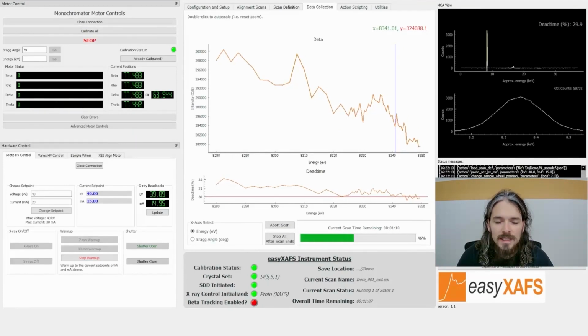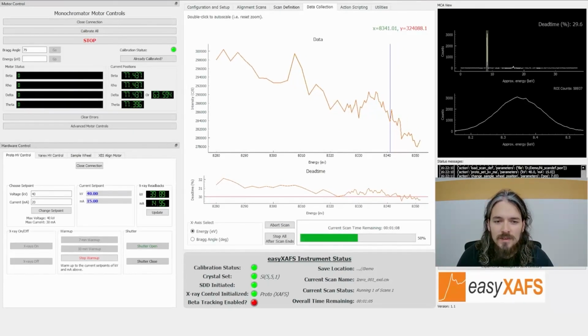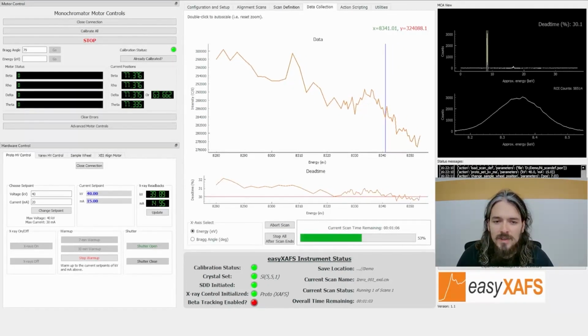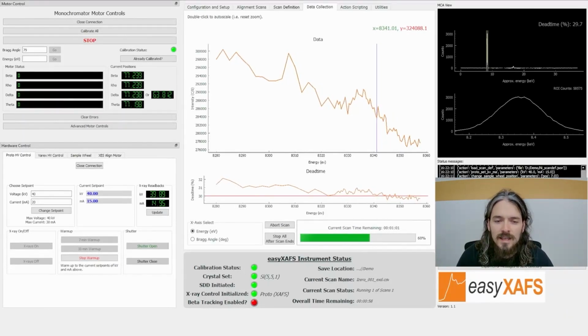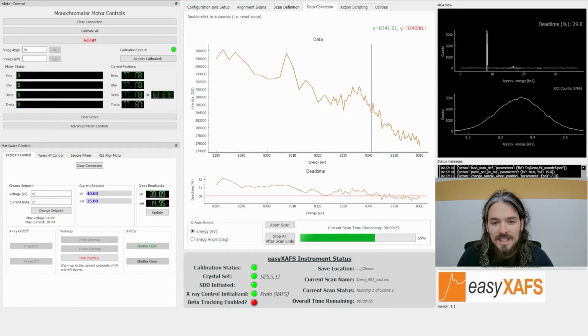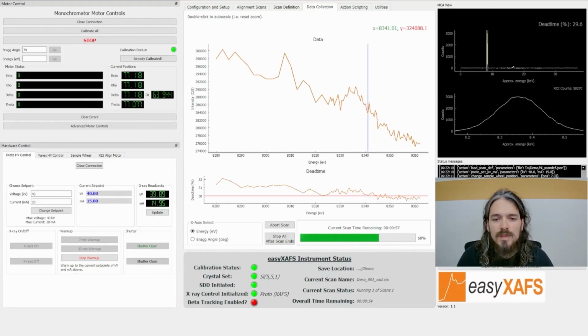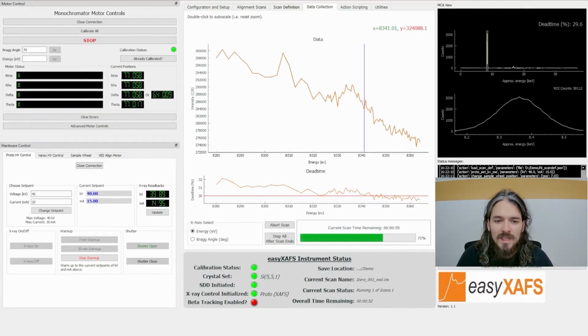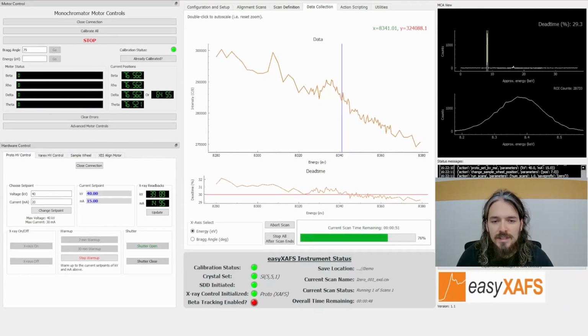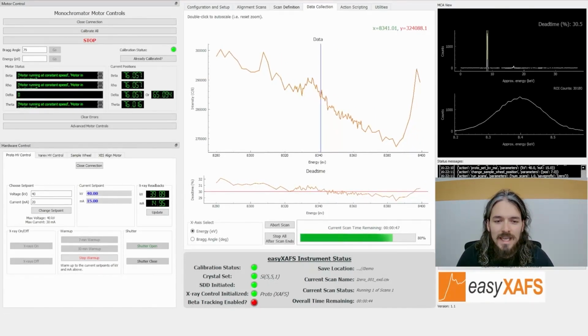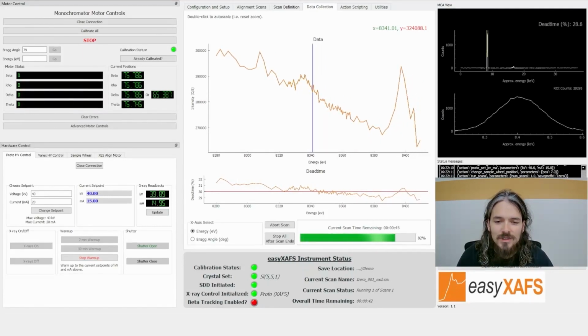So in the middle, you can see beneath the main plot, there's a plot of the dead time. So it's around 31%, and the target dead time is around 30%. On the I0 position, without any sample to absorb the X-rays, we reduce the beam power to avoid saturation. So before the measurement switches to measuring the samples, that's why it's set to increase the beam power, to increase the count rate. Okay, so with that, we'll let the data continue to collect.